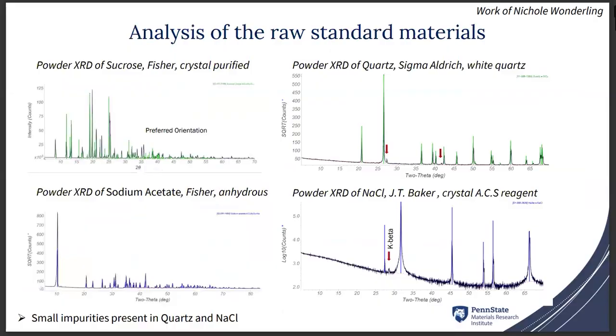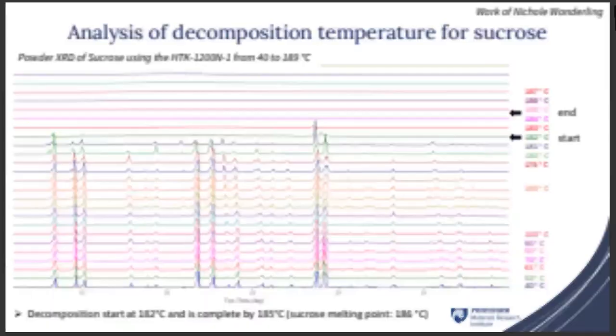So the first step for this analysis is to just analyze the pure material using XRD and make sure that the compound we are using is the real compound. This was done on the sucrose, the quartz, the sodium acetate, and the sodium chloride, confirming that this is the material we are interested in.